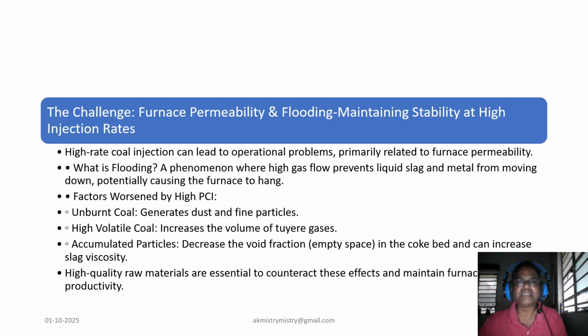However, injecting coal at such high rates introduces significant operational challenges, with the most critical being the impact on furnace permeability. Poor permeability can lead to a phenomenon known as flooding, where the high upward flow of gas prevents the downward movement of the liquid slag and metal. This can cause the furnace to hang and disrupt production.